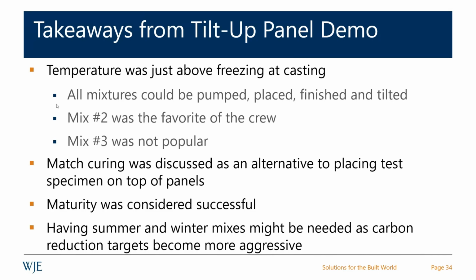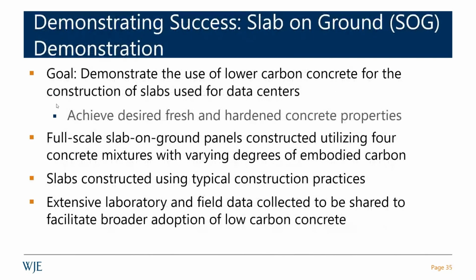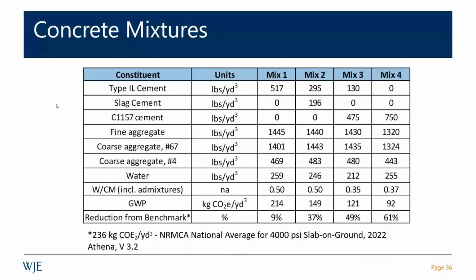We did a slab on grade demo. Similarly, we had mixes where our control was a 9%, and then you can see these fairly significant reductions. Again, mix 2, you'll notice, is a slag cement mix. So low cementitious content all the way. If you look at these cement contents, 517 pounds total cementitious, but the slag right here, and then this one had a little bit of cement, and then this nothing. It's just the 1157. You can just see a lot of carbon reduction there.